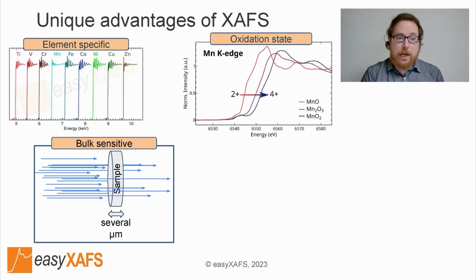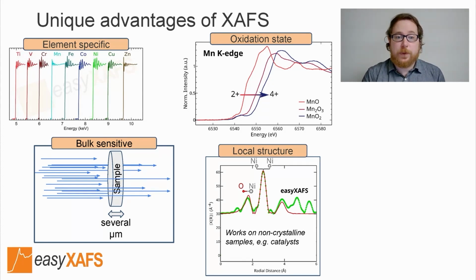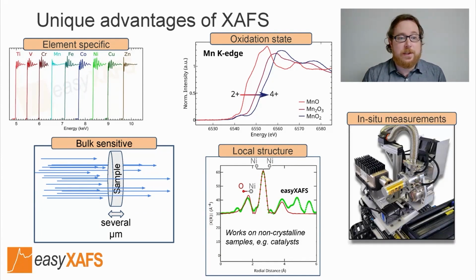Third, in the XANES, the near-edge region that we talked about, the different oxidation states have unique fingerprints. This makes it well suited for linear combination fitting to extract oxidation information on an unknown sample, or to simply track changing oxidation that's going on during a chemical reaction. Fourth, XAS only probes the local structure. What that means is that it works well on crystalline, nanocrystalline, or amorphous samples. There's no long-range order required in order to get an XAS spectrum, such as would be the case, for example, with X-ray diffraction. Lastly, since it's hard X-ray in, hard X-ray out, it's very well suited for in situ measurements, where the absorption by just the material and the geometry of the cell can be challenging for some other techniques.